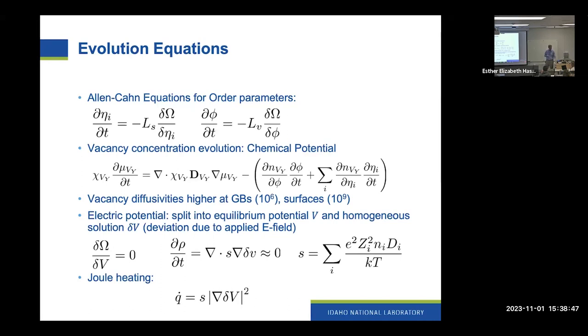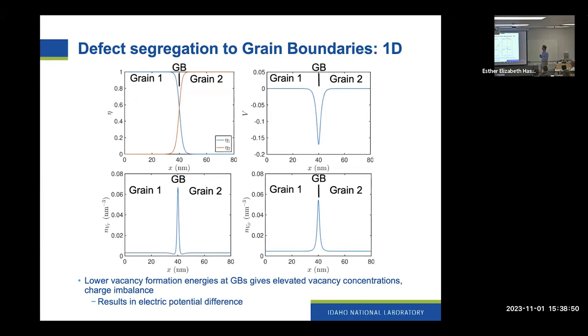and the electrical conductivity. One of the things that we wanted to capture in our model is defect segregation, and to understand what effect that would have on the charge at grain boundaries. This is a picture of the order parameters that I showed before, and we have a grain boundary at the center of this domain. We assume that there's a lower formation energy for vacancies at the grain boundaries, and that's going to result in an elevated concentration of these vacancies. And because these vacancies are charged, that's going to lead to an imbalance of charge and an electric potential gradient. That's what you see here: the defect densities for vacancies and oxygen vacancies, and the resulting electric potential that forms.